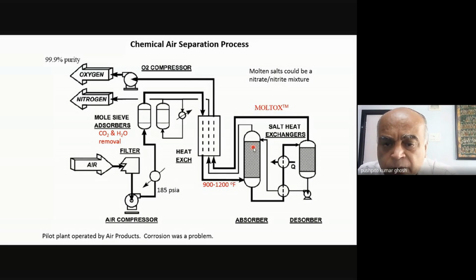And what has been found is that at a particular temperature, let's say 900 to 1200 degrees Fahrenheit, oxygen has high solubility in this molten salt. Then you take it from this bed into what is known as an absorber, because you're absorbing the oxygen, and then you take it to a desorption unit, where you heat it up to higher temperatures. At those higher temperatures, the oxygen loses its affinity for the molten salt, and you can take out the oxygen.